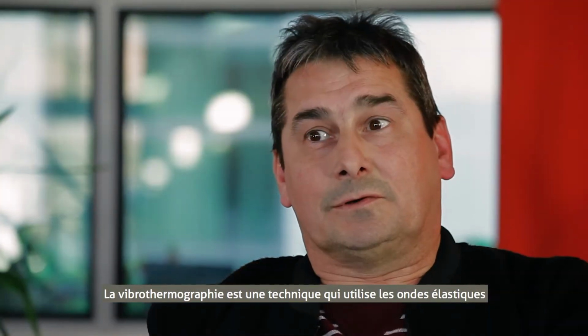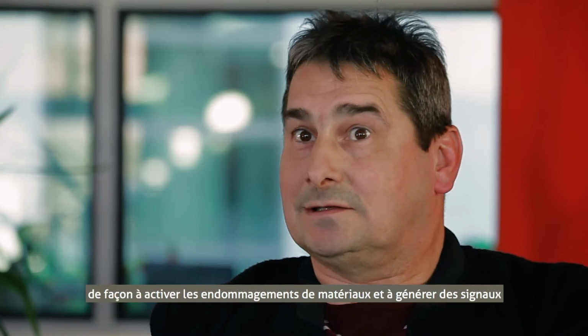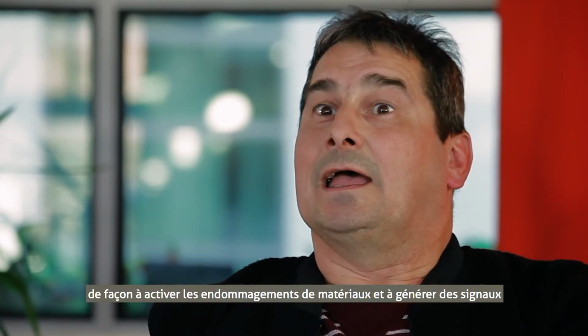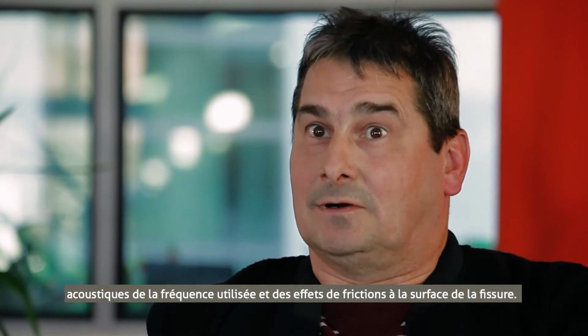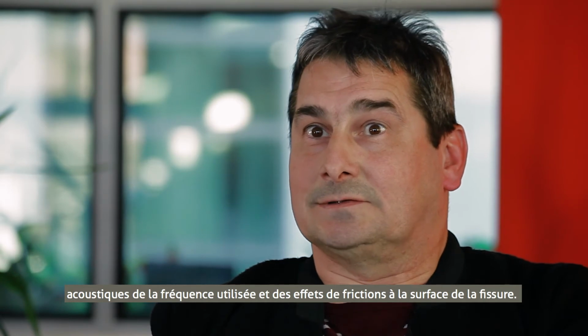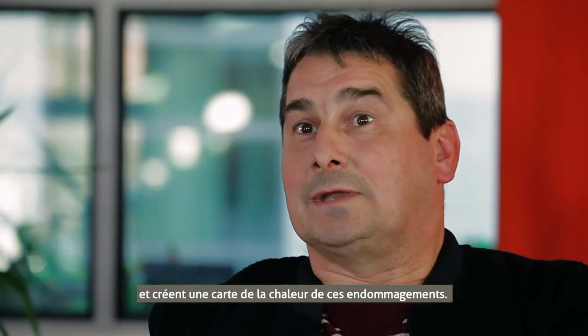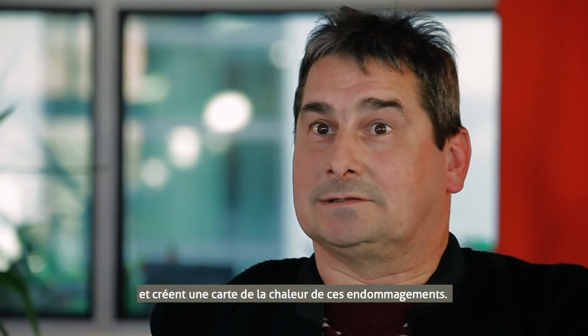Okay? So our interest is in nonlinear acoustics and in vibrothermography in order to characterize and detect defects such as delaminations. Vibrothermography is a technique that actually uses elastic waves in order to activate a damaged component and to generate harmonics of the frequency that we apply, and also frictional effects at the crack surfaces. Those frictional effects then generate heat and create a heat map actually of the delamination itself.